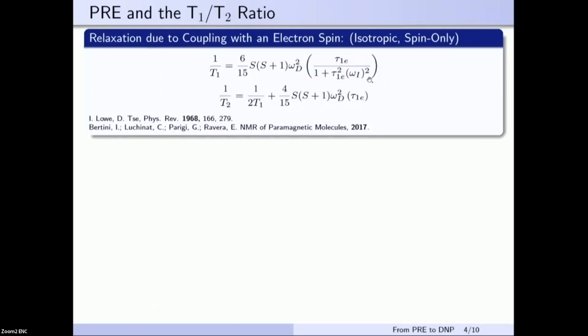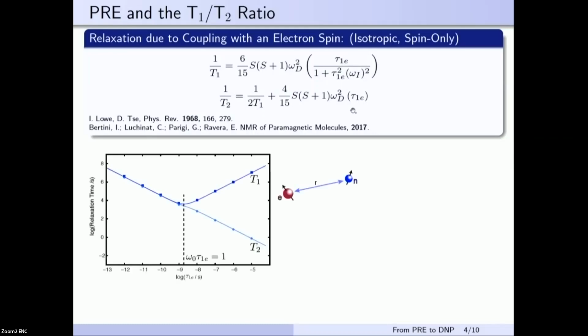Now, the interesting part here is that because this is a rigid solid, there are no structural reorientations that could cause relaxation. Instead, the source of the fluctuating fields that cause relaxation of the nuclei are the random fluctuations of the magnetic moment of the electron spins themselves. The electron spins are fluctuating because of their own relaxation, and this is felt by the nuclei as a fluctuation of the interaction. The correlation time that describes this fluctuation is the electron relaxation time, T1e. I'm writing here tau 1e because there are also coherent effects that are not strictly speaking relaxation that we know can contribute, but anyhow. The T2 relaxation rate has an additional term, which is proportional to the spectral density at zero frequency.